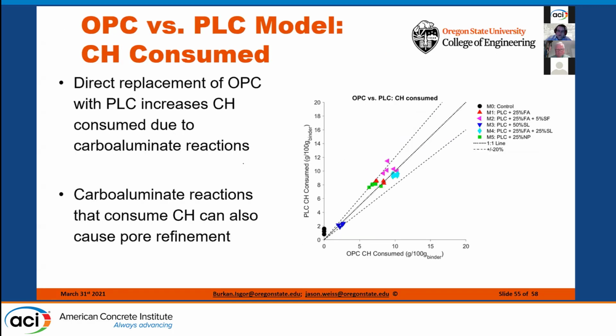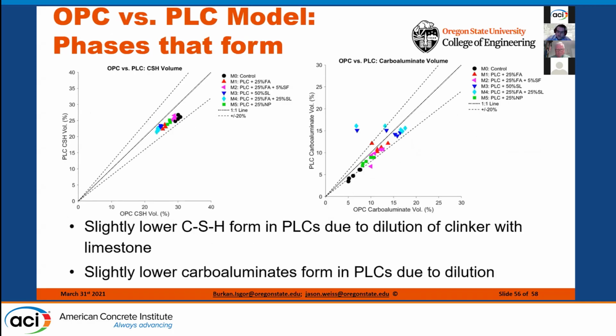We now start to do a direct comparison where we compare the amount of calcium hydroxide consumed. And what we notice here is as you start to get more of your siliceous materials into the system, we're going to be consuming more calcium hydroxide. But again, we've had very, very good comparison between the model, the experiments, and what we're seeing with the OPC.